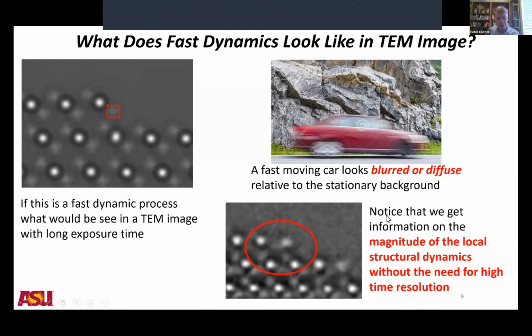And what's interesting about this is that we're getting very highly localized information at the atomic level about structural dynamics, okay? But we don't need high time resolution to see it. So we can measure the magnitude of the structural distortion that's associated with the structural dynamics without necessarily having ultrafast. We don't need to have picosecond time resolutions to see it.